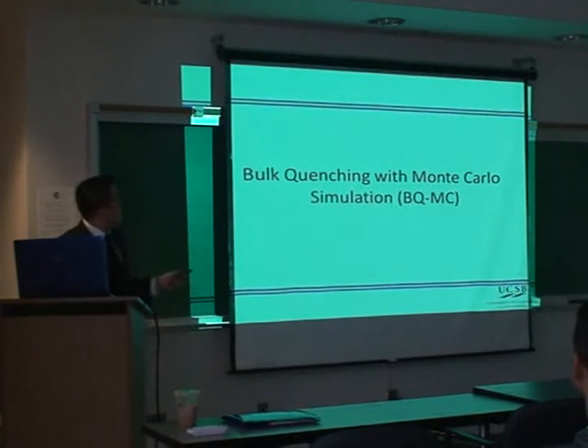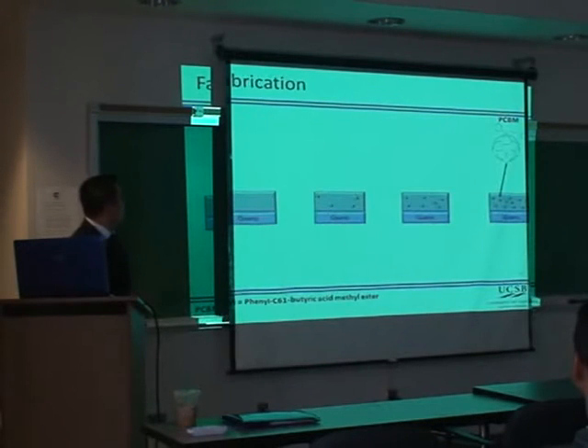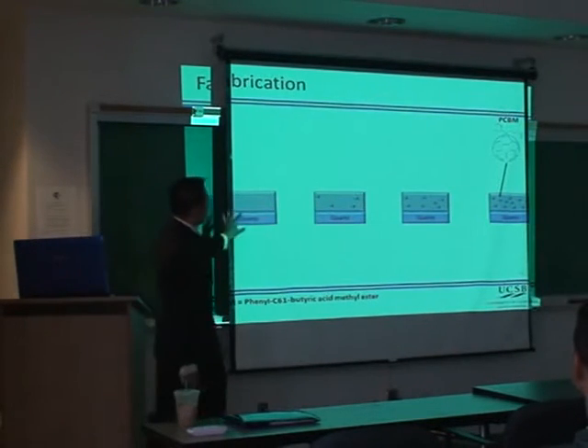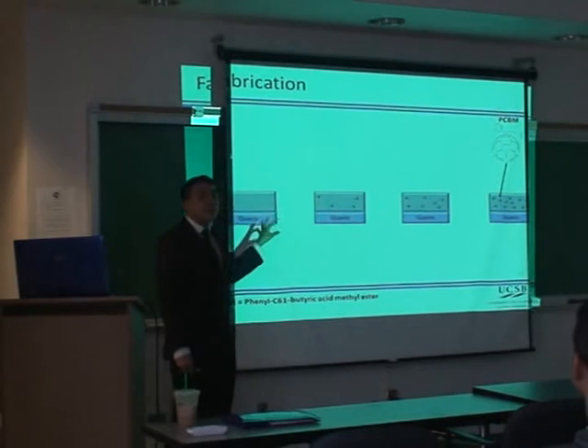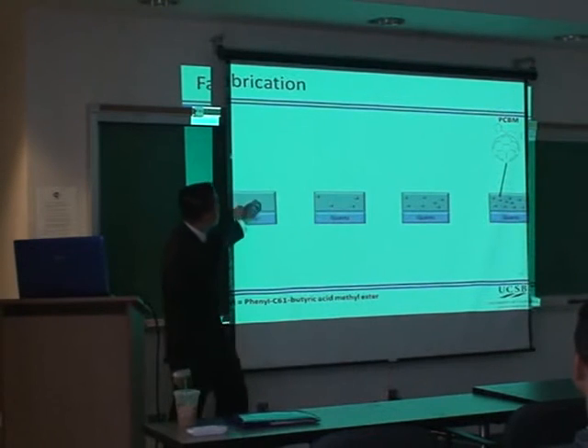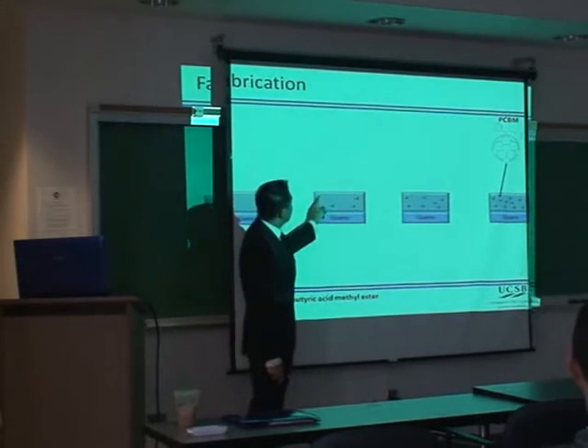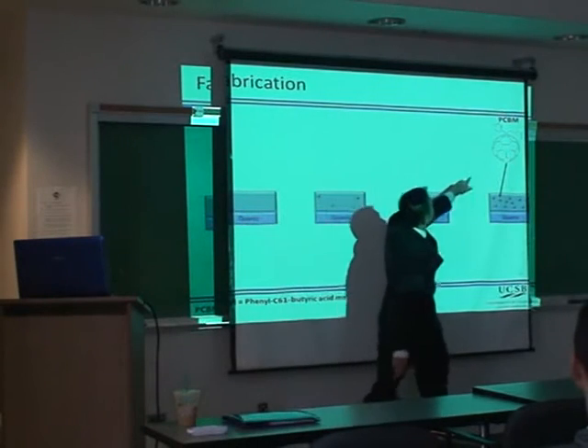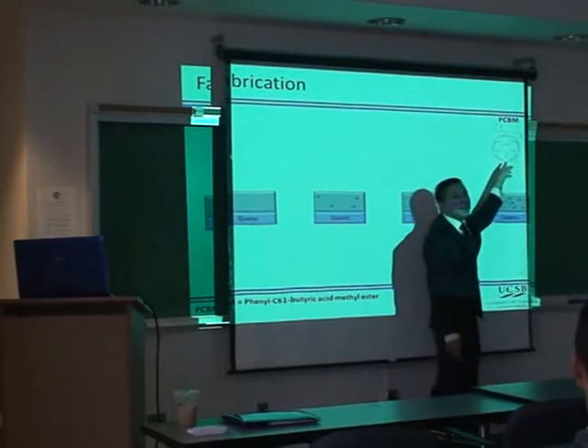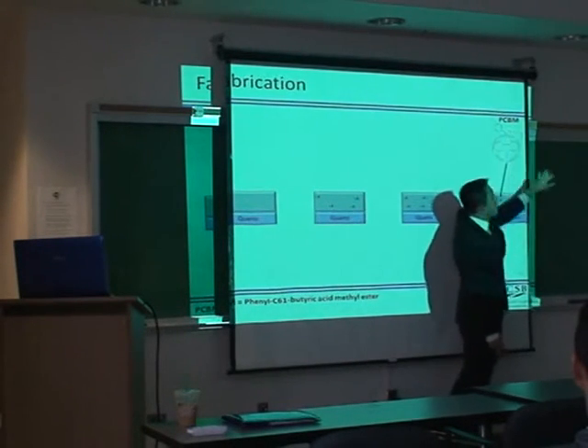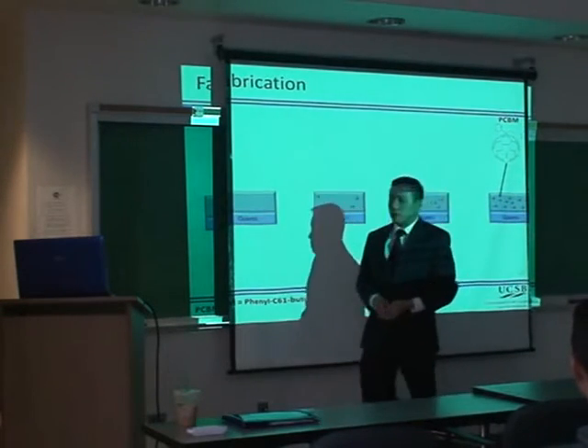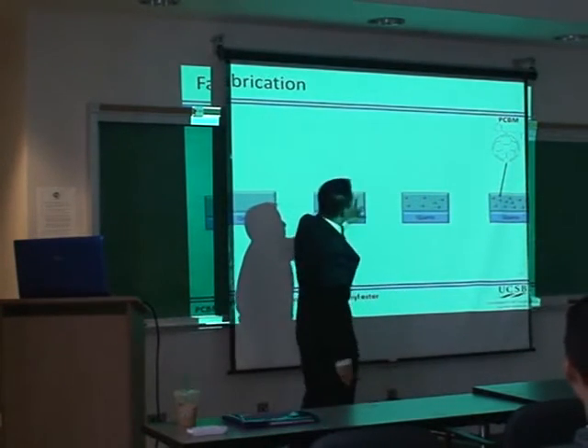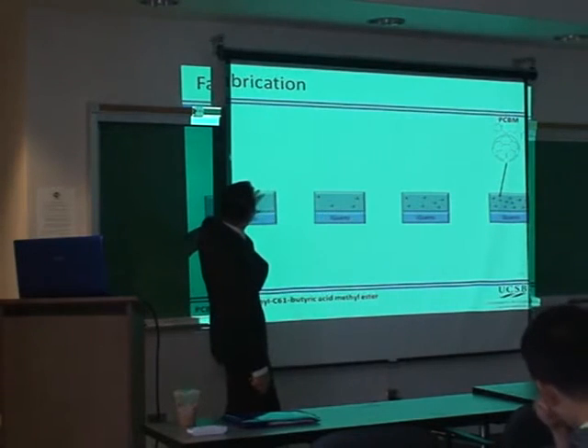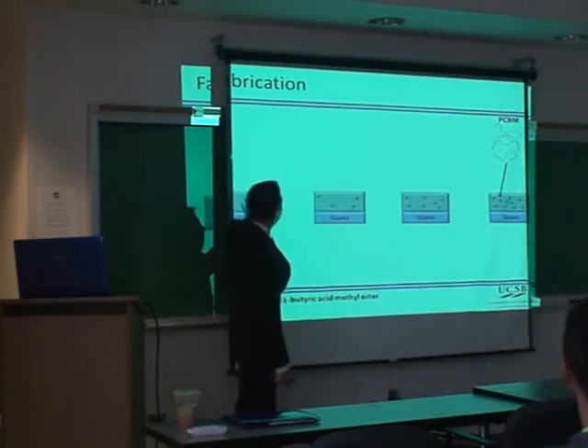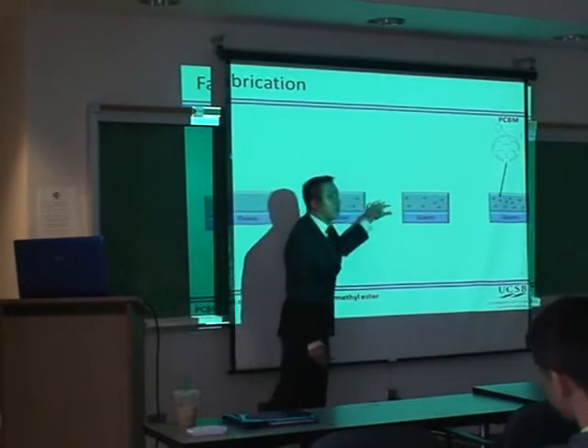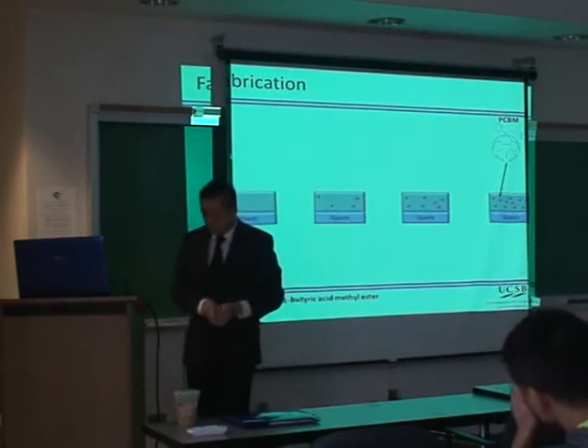So, bulk quenching with Monte Carlo simulation. The preparation is similar. We just use spin coating, but now we add in an extra material. So these balls are PCBM. It's very similar to C60, but we've added some additional groups that make it soluble in organic solvent. So we mix different concentrations of our organic semiconductor with the PCBM, and we're able to produce different films with different concentrations of PCBM.